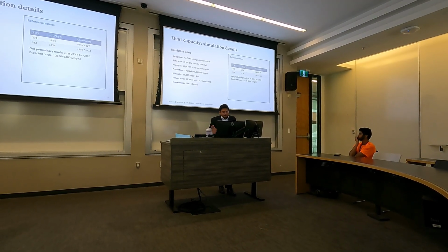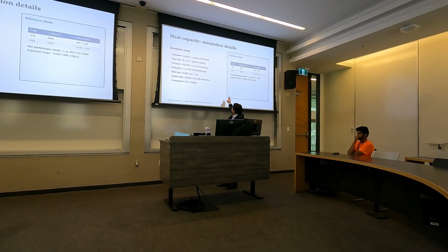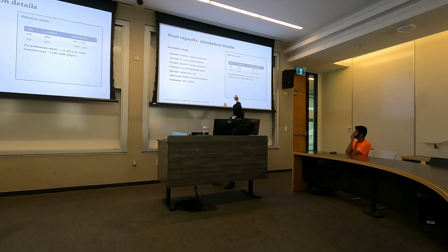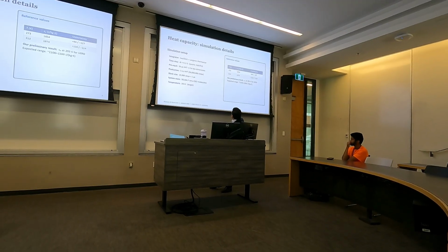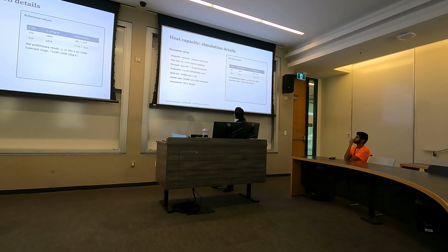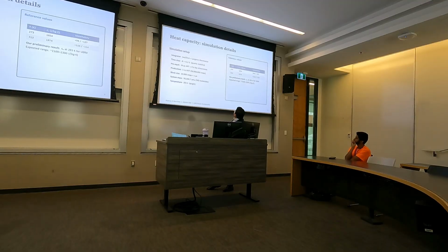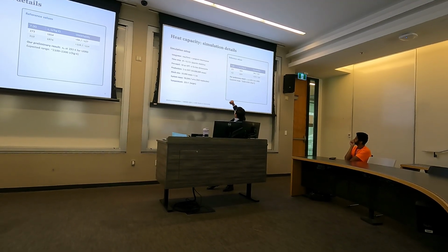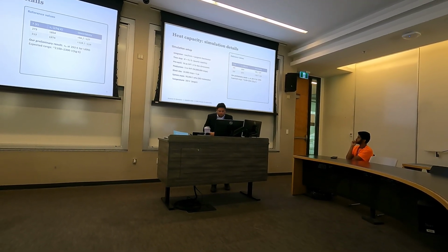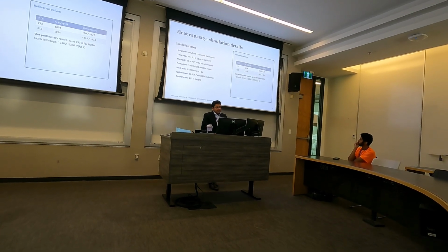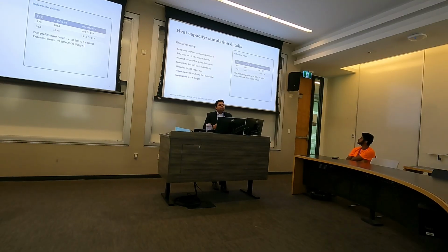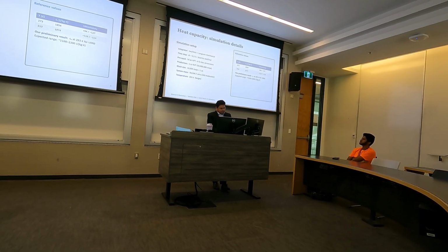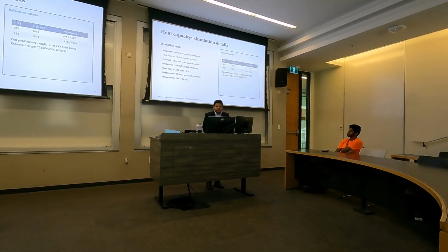This particular calculation is a preliminary result that we have at 293 Kelvin. For the uncured system, we expect the value to be around 2000 to 2300 joules. And those are the values that I'm getting for 293 and 313, which are a little off, but I guess because for these systems we need more replicas in order to get an actual value. So this one is just from one of those, and we are still running a few of these as we speak.